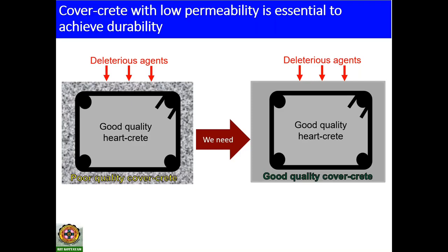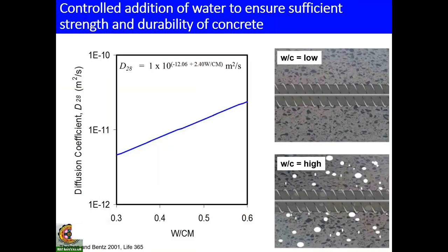In order to achieve good quality covercrete, what do you need? You should have proper construction practices as well. You should use supplementary cementitious materials. You should do proper mix design. You should do enough compaction. You should provide cover blocks. You should also provide good curing for this concrete. Then, controlled addition of water is essential to ensure sufficient strength and durability.